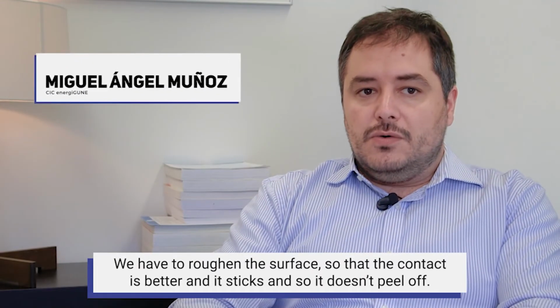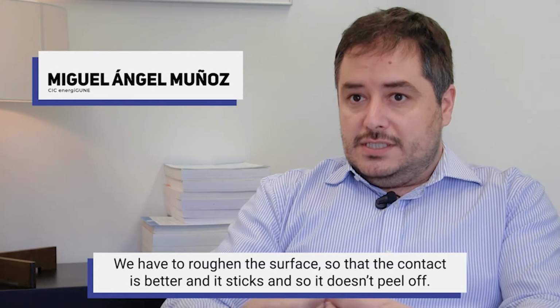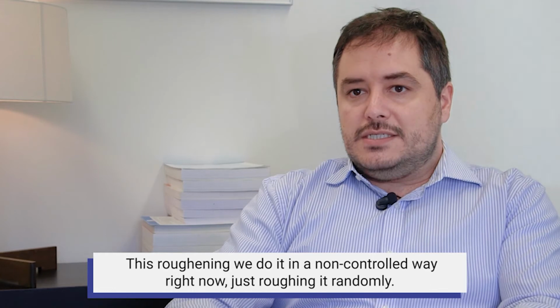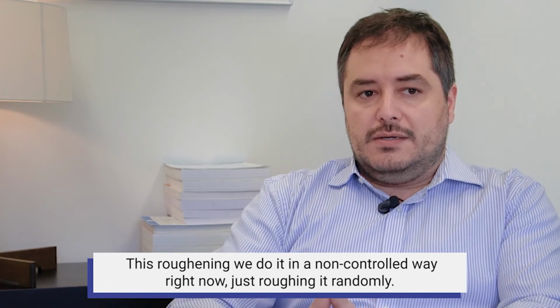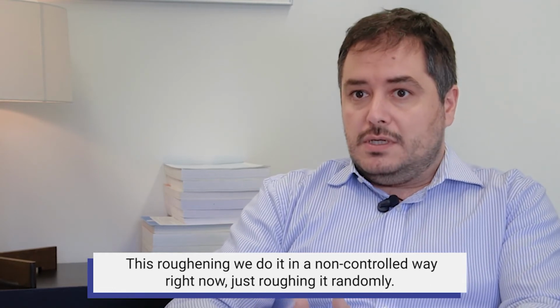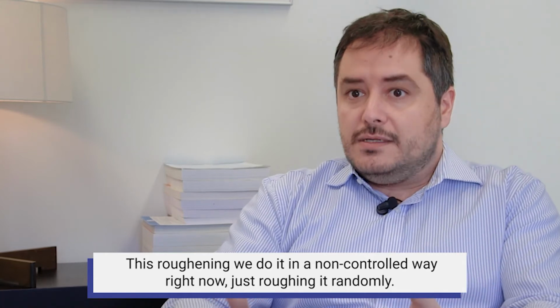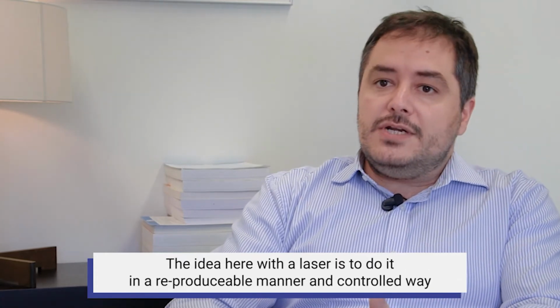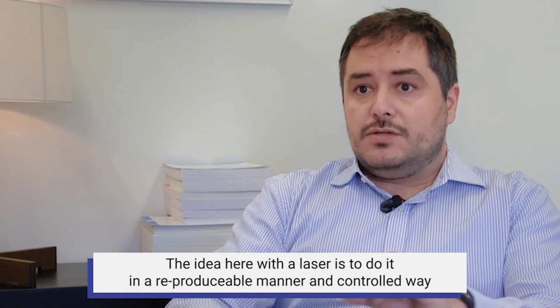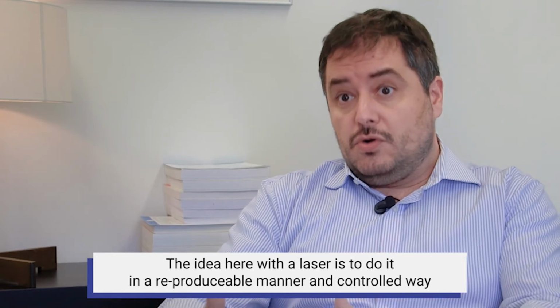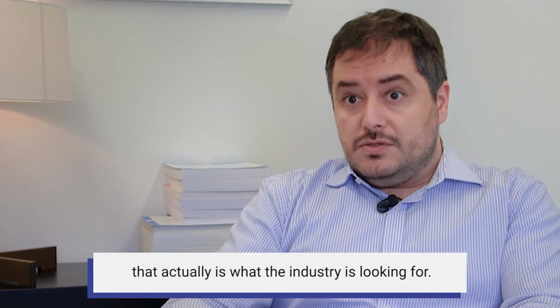We have to roughen this surface, so the contact is better and it sticks, so it doesn't peel off. This roughening, we do it in a non-controlled way right now. We just rub it randomly. The idea here is to, with the laser, do it in a reproducible manner and very controlled way. That actually is what the industry is looking for.